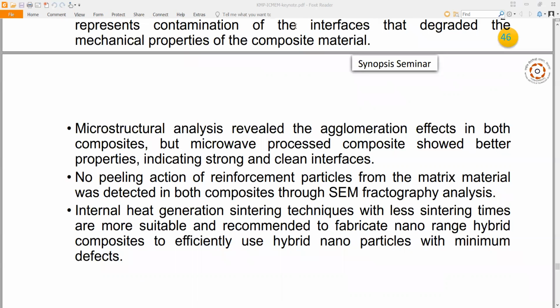Then microstructural analysis revealed agglomeration effects in both composites, but microwave processed composites showed better properties, indicating strong and clean interfaces, and no peeling action of reinforcement particles from the matrix material was detected in both composites through SEM fractography analysis. Then internal heat generation sintering techniques with less sintering times are more suitable and recommended to fabricate nano-range hybrid composites to efficiently use hybrid nanoparticles with minimum defects.